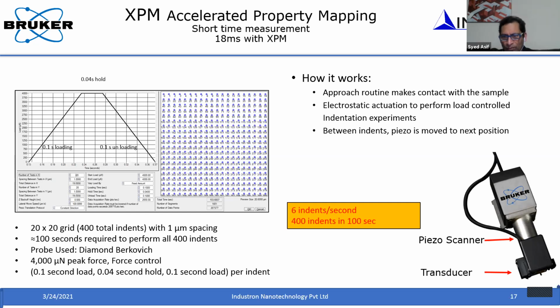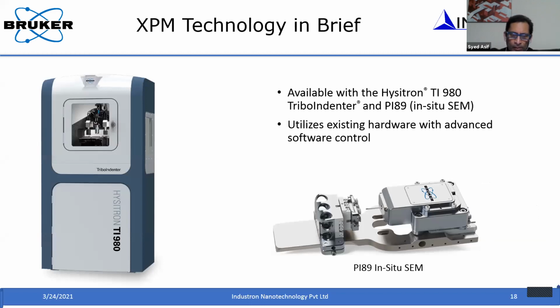To do that, a very important thing is that you need to have the right control system and the right hardware. In the system that we use, the Hysitron or the Bruker system, you have this piezo scanner capable of moving the transducer at a very fast rate and in a very controlled manner. The transducer has a dynamic response that can work at a much faster rate, and the control system should be capable of doing this. With that combination, you should be able to do this mapping in a traditional way, measuring the indentation depth response as a function of load, processing the data and calculating the properties as a map.